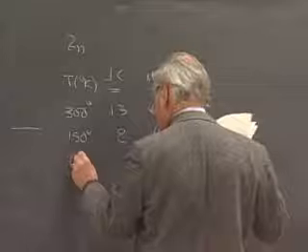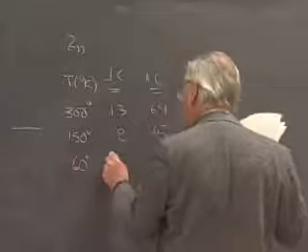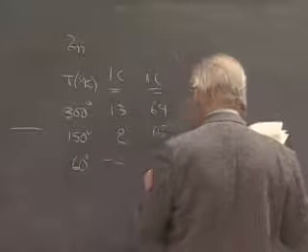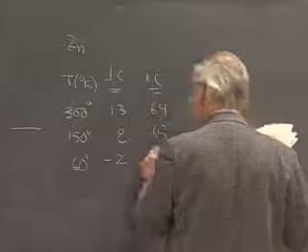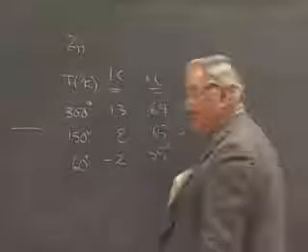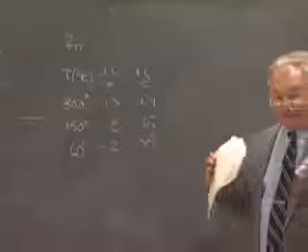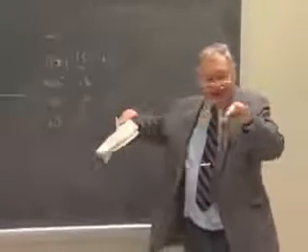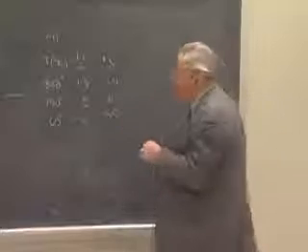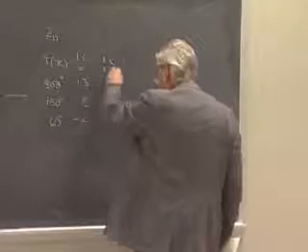At 60 degrees K, perpendicular to C, the thermal expansion is negative and has not dropped terribly much at all parallel to C. So this is a hexagonal close-packed structure, a lot of action and strange things going on in the plane of the close-packed layers, but not very much change in a direction perpendicular to the layers.